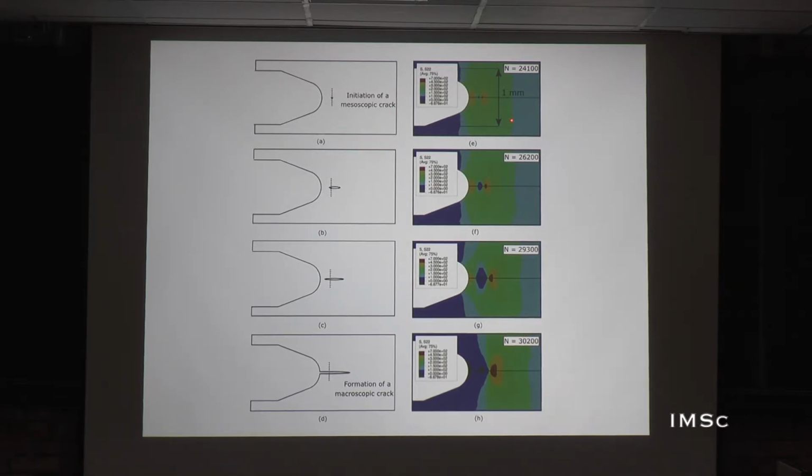This is from the simulation, the contour plots. What we are showing is the opening stresses, the opening traction. This is the notch tip, and ahead of that we see that as the crack forms here, the high stresses, indicated by red color, are on the right hand side of it. On the left hand side you have high stresses, but not as high as on the right hand side, and this process here is becoming slightly low triaxiality, and here you have high triaxial growth of crack and subsequent formation here. All colors have become blue, indicating that the surface has become completely traction free.